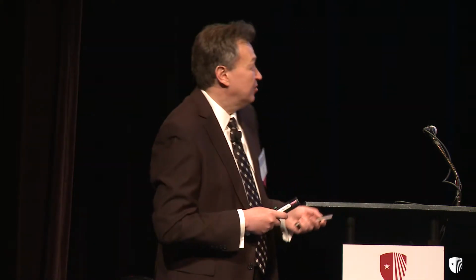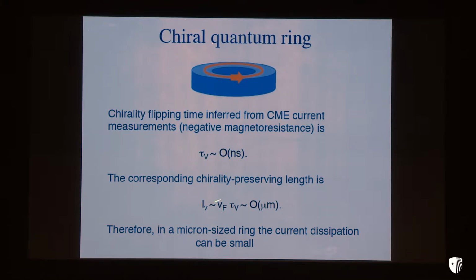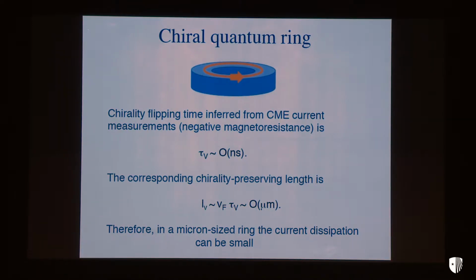It can never work. However, what you have to remember is that what matters is not the coherence time per se. It is the ratio of coherence time to the time over which you can implement a quantum gate. And the time over which you can implement a quantum gate in a superconducting qubit is limited by the superconducting gap, so loosely speaking, the binding energy of the Cooper pair. Whereas in these materials, the time over which you can manipulate this current is lower than 1 picosecond.